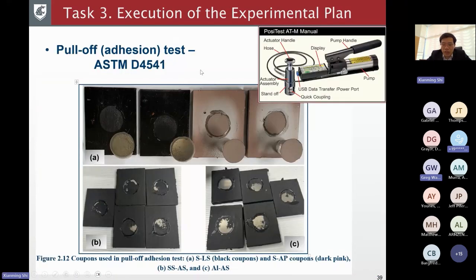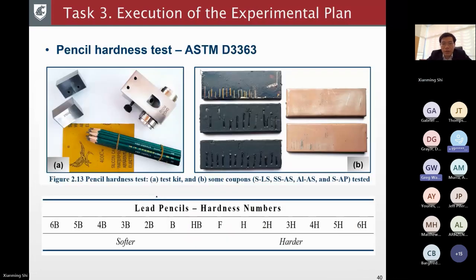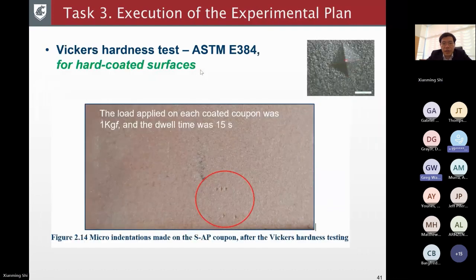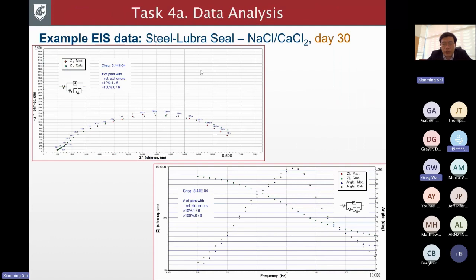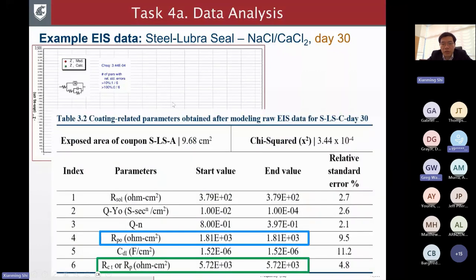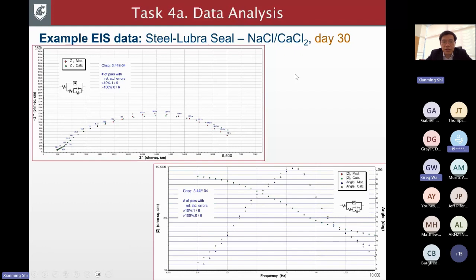Yet another set of tests was the adhesion test, basically a pull-off test to measure the adhesive strength of the coating to the metal. And then yet another one is the pencil hardness test, and the Vickers hardness test, which is for the really hard surfaces. Basically, you measure how big the dent is when 1 kilogram-force is applied onto that surface for 15 seconds. And again, we have basically hundreds and hundreds of these EIS results, because at different times over 31 days, we measure them periodically. This gives us a lot of insights in terms of how the coating deteriorates and how the corrosion initiates and then propagates.